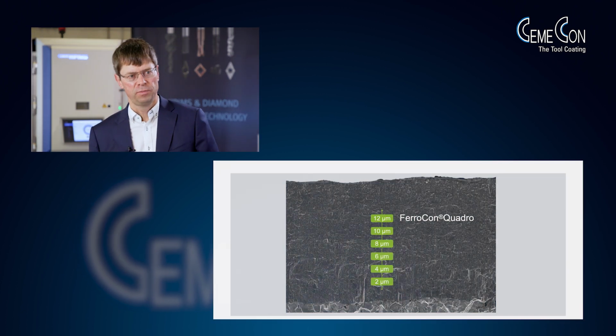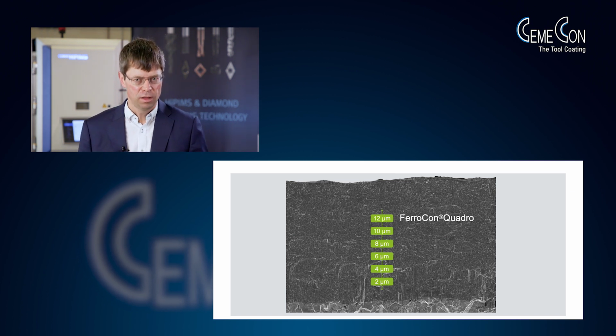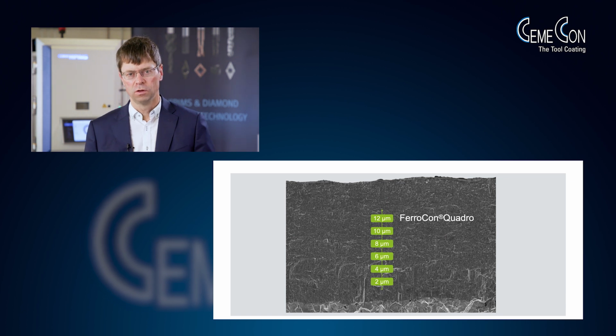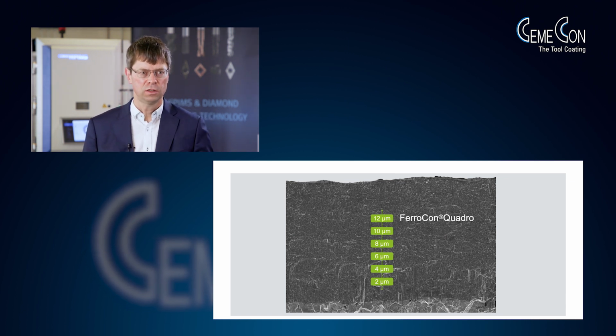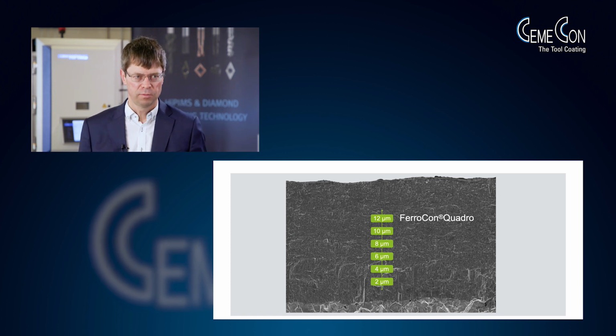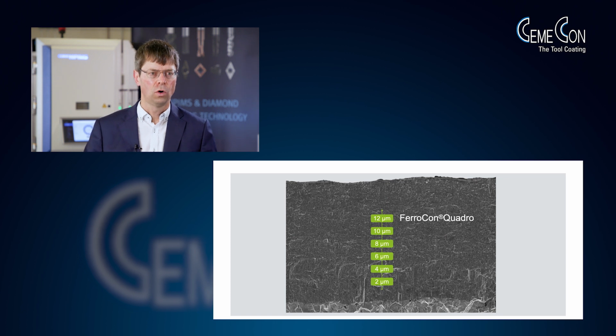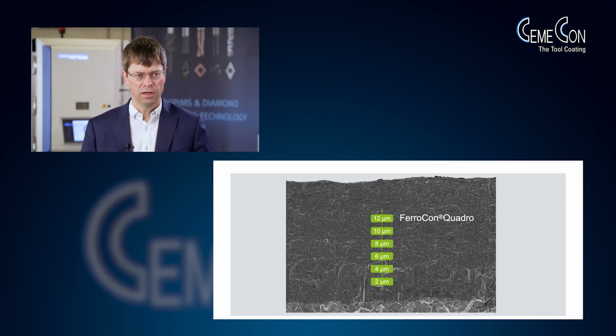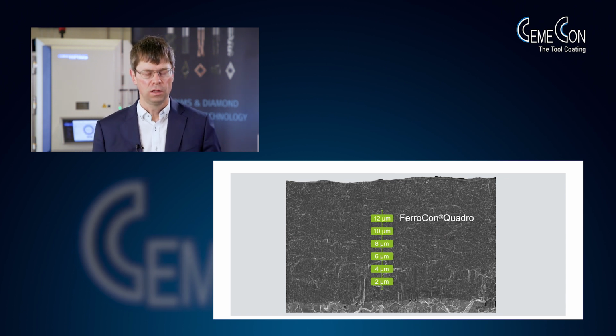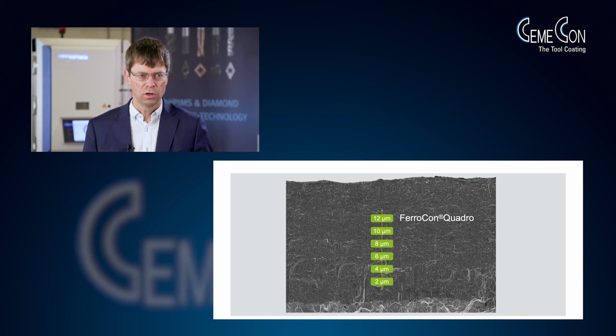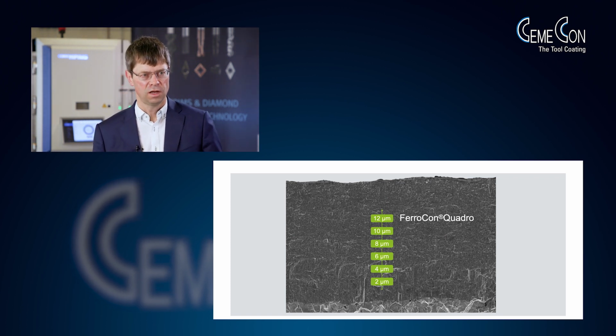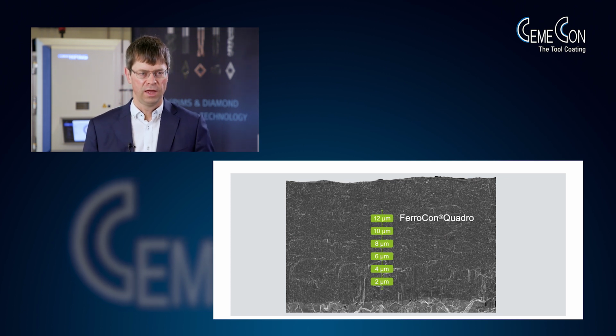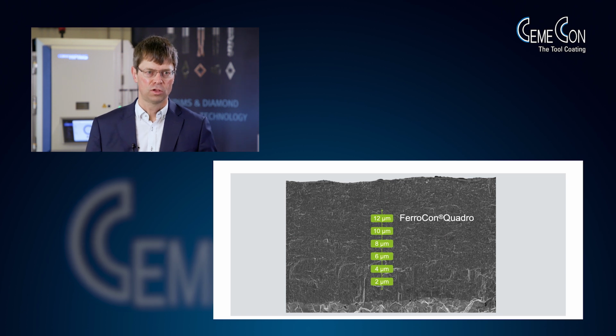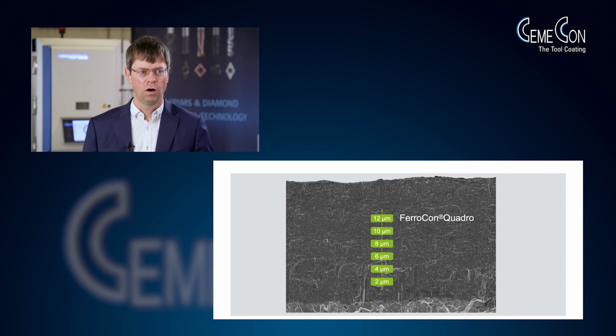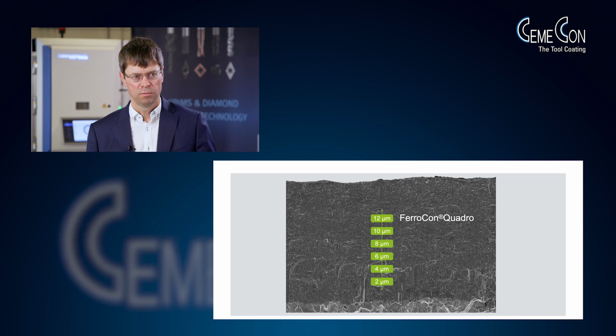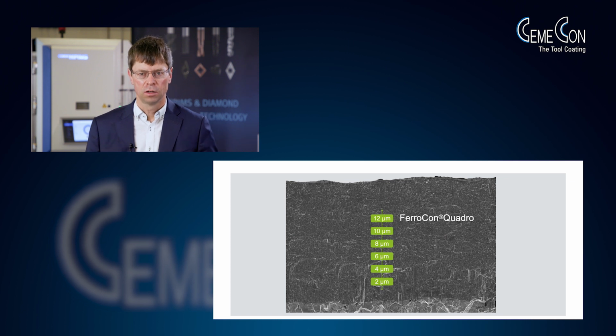Another very good example from a fully different type of tool, indexable inserts, is FerroCon Quadro, the first product with 12 micron PVD coating, a so far fully impossible coating thickness. And here you see through all the 12 micron an undisturbed morphology, no voids, not in the coating, not on top of the coating, very small grain sizes, giving a very good toughness. And just being capable of having 12 micron on the carbide substrate is a very nice illustration that obviously stress management in HiPIMS is working on commercial cutting tools.